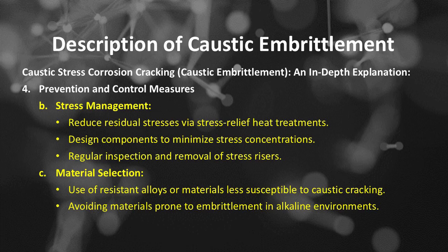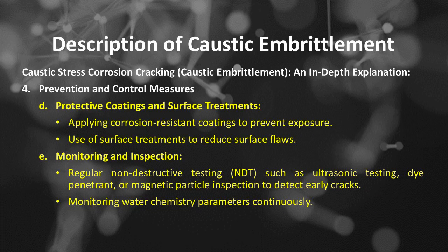Prevention and control. Number C, material selection. Use of resistant alloys or materials less susceptible to caustic cracking. Avoiding materials prone to embrittlement in alkaline environments. Prevention and control. Number D, protective coatings and surface treatments. Applying corrosion-resistant coatings to prevent exposure, use of surface treatments to reduce surface flaws. Prevention and control. Number E, monitoring and inspection. Regular non-destructive testing or NDT such as ultrasonic testing, dye penetrant, or magnetic particle inspection to detect early cracks. Monitoring water chemistry parameters continuously.